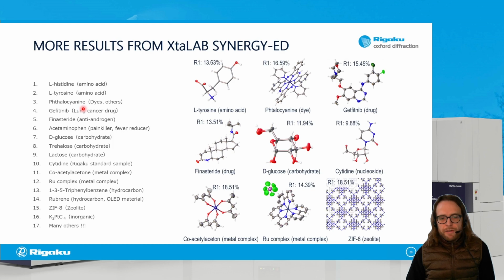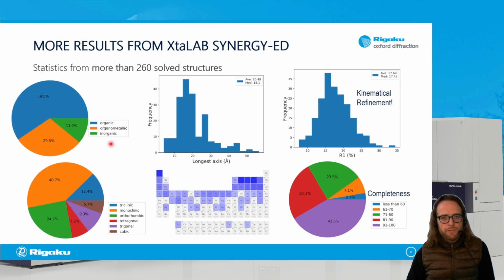And by now, we have measured samples for many customers, over a wide range of different sample classes. Here you see just a few examples from all kinds of different systems. Here's some statistics. We have more than 260 structures solved now, and actually increasing very, very quickly. And you can see that we cover a wide range of different classes of samples, of crystal systems, even including relatively long unit cell axes, now also including more and more heavy elements. So this is expanding very quickly.